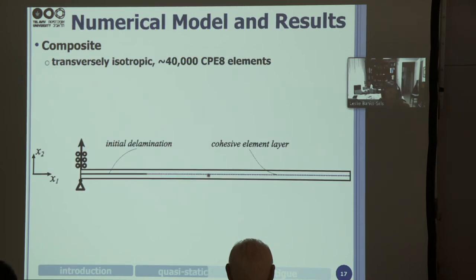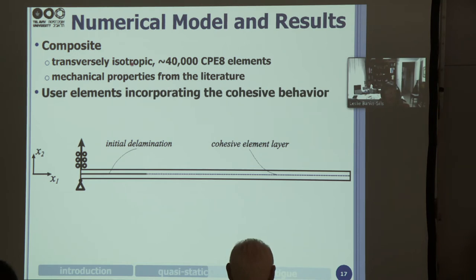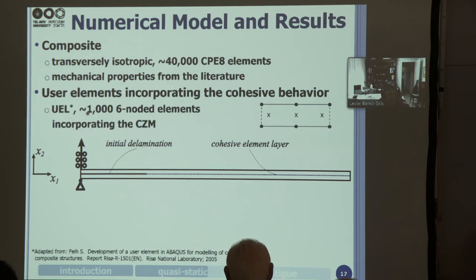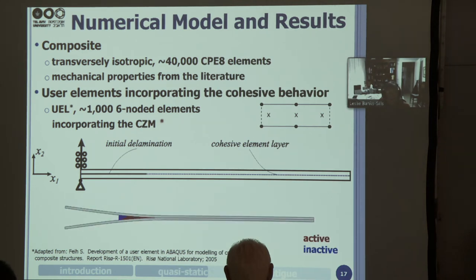So here's our composite DCB specimen. Here is the initial delamination. We have 40,000 plane strain elements. We're using Abaqus. The material is transversely isotropic, and we obtain the mechanical properties from the literature. We incorporate a user element for the cohesive behavior, with cohesive elements all along the interface between the upper and lower arms of the specimen. We have 1,000 user elements, which are 6-noded elements with 3 integration points, and it incorporates the CZM, the cohesive zone.